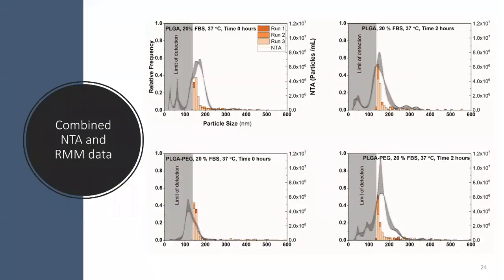What we can then do is apply both of these two techniques together to analyse samples. And the greyed out area in these particular graphs is the size range of data that we can get from the nanoparticle tracking analysis that the resonant mass measurement effectively cannot see. And what this allows us to do is determine that a lot of the stuff that we saw sub 100 nanometers by NTA is definitely protein, and other smaller aggregates, and isn't necessarily what we're interested in here.